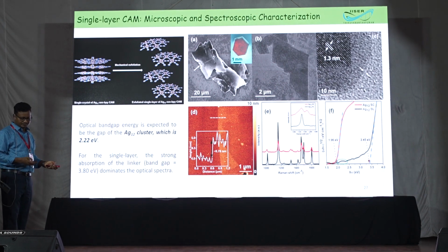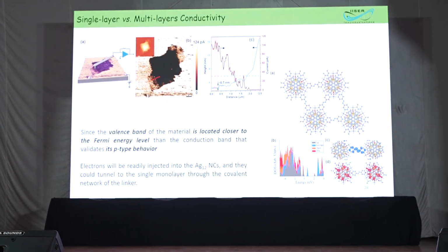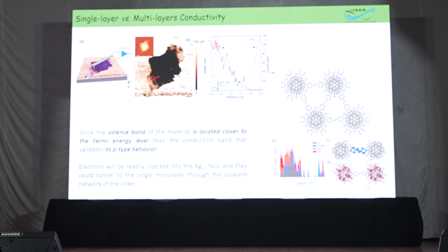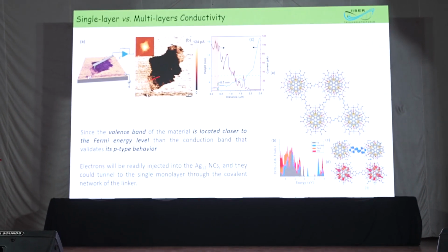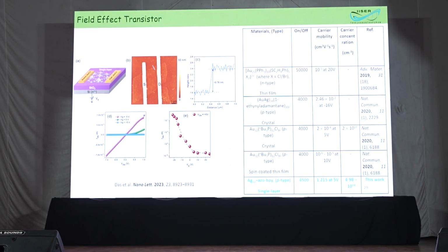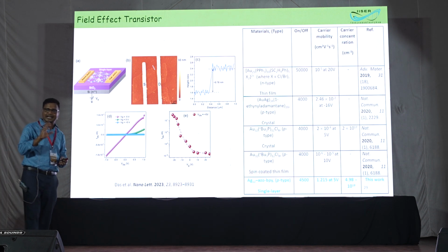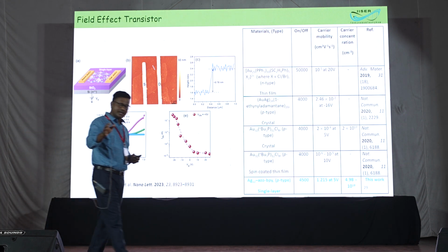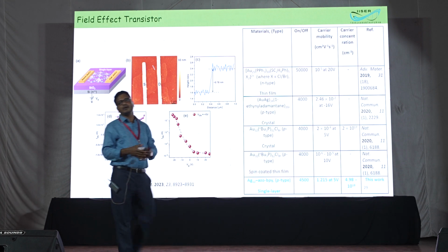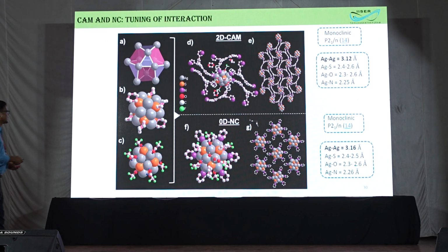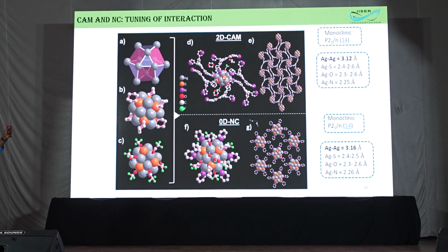An interesting feature is that between multi-layer and single layer there is a change in optical properties. Then we did a theoretical calculation showing a p-type semiconductor, and we made a device out of the single layer, which shows a very good FET device. Compared to other clusters, the on-off ratio is very high, as are the mobility and carrier density. So not only are we linking the cluster into an extended solid and making a single layer, we use it for a field effect transistor.